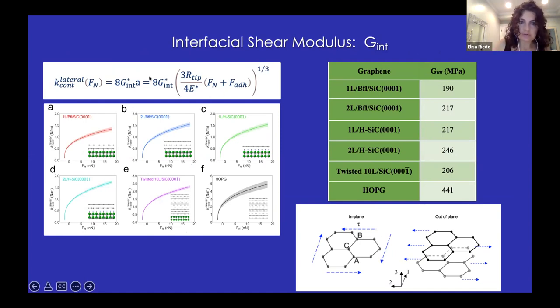Since the contact radius is a function of the load, adhesion, and Young modulus, which we can measure with the modulated nanoindentation method that I showed to you before. So we really can measure the Young modulus of the interface, right? We know the tip radius. So all this part is known. We can obtain the interfacial effective shear modulus. How do we obtain this? We just plot the experimental lateral contact stiffness as a function of the load, as you can see here, and then we use this same equation to fit the experimental data.